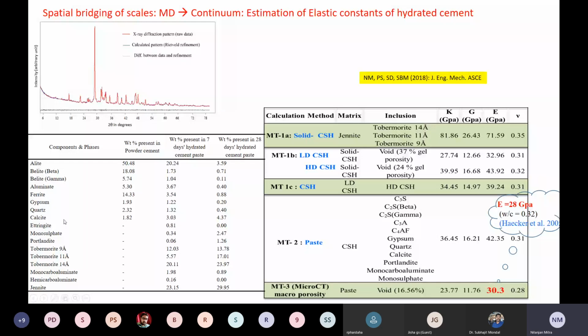I also showed you something about ettringite, something about tobermorite, and so on and so forth. You see the different types of structures that are in there. So these are what is present within the powdered cement. As you put in water, eventually you get different types of compounds in here. And after 28 days, in what we know as the hydrated cement paste, we get different types of compositions. These are different weight percentages. So we take all these weight percentages and put them in our chart.